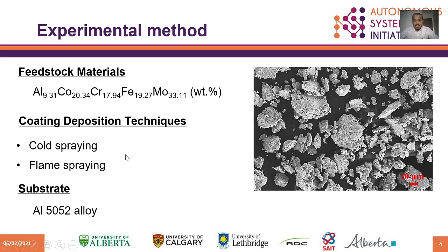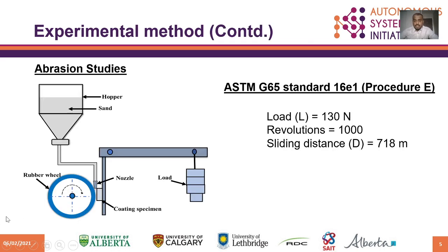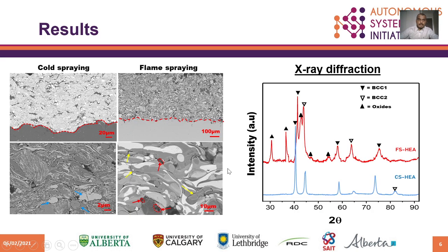The flame spray, on the other hand, has a high temperature heat source where particles melt and the molten particles are accelerated towards the substrate, forming coatings. The substrate used in this study is aluminum 5052 alloy. Abrasion studies for these coatings have been performed to understand the coatings' reliability under sliding and abrasion movement according to the ASTM G65 standards.